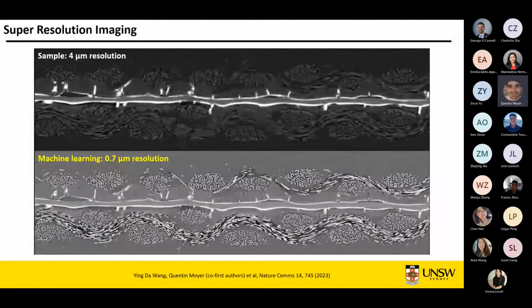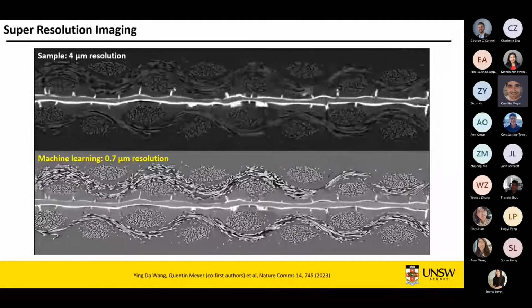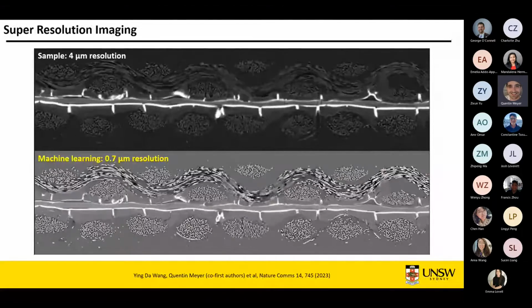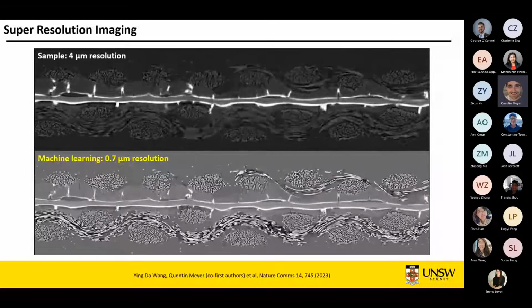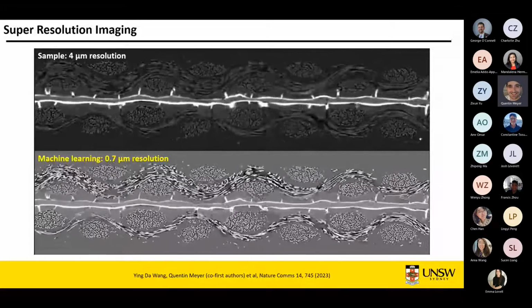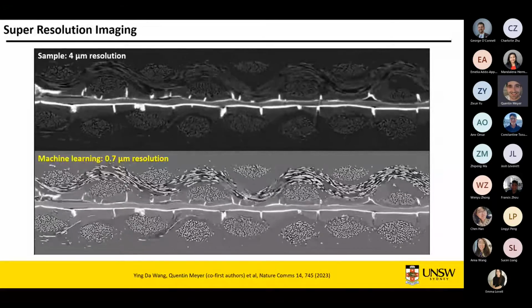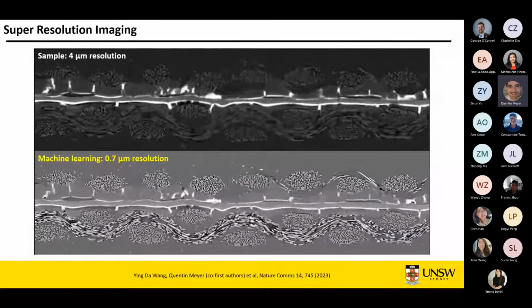So what we propose to do is called super resolution imaging, which has emerged for characterization of rock-based samples. You take a small area of this sample, you scan it with a higher resolution, and then you use machine learning to improve the resolution of the entire sample.